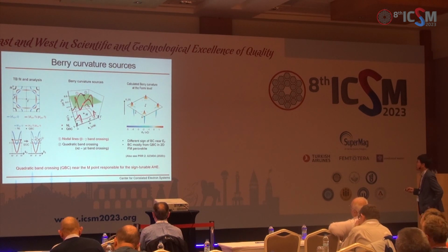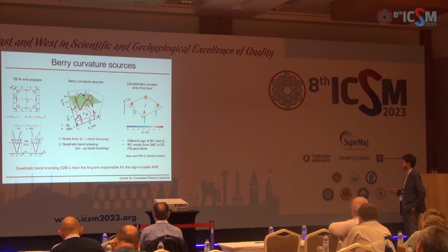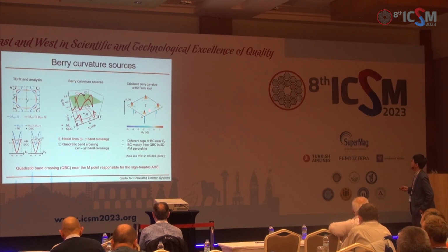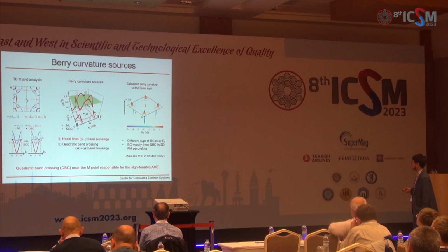So based on this tight binding fit, you can calculate Berry curvature. And what's shown here is a calculated Berry curvature from the tight binding band. And here is a Brillouin zone, and Berry curvature mostly comes from these four corners of the Brillouin zone. And it turns out that most of the Berry curvature actually comes from this quadratic band crossing.